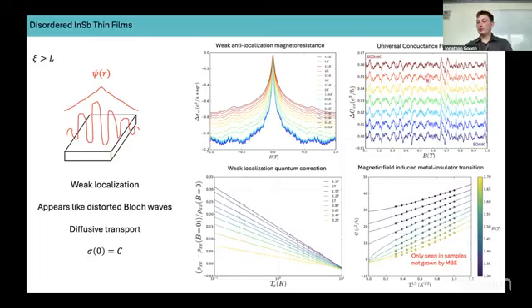We also see universal conductance fluctuations in very small samples. Again, this is essentially these self-interfering paths contributing to your measured conductance, which show up as something very similar to noise. We also see a temperature dependence in these samples due to the temperature dependence of the phase coherence length. Obviously, the larger the phase coherence length, the more these looping paths dominate. So as you cool down, you get this enhancement in weak localization. And in very, very clean samples, it's possible to observe a true metal-insulator transition, typically observed in 3D systems. However, this was only seen in extremely clean samples not grown by molecular beam epitaxy.